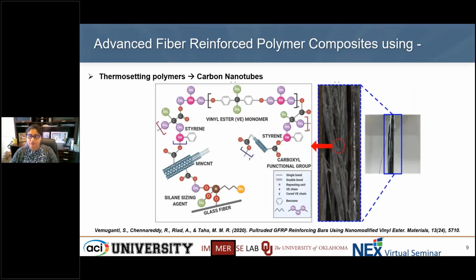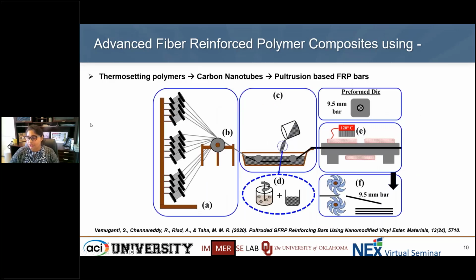One of the primary things we've seen with bars, for example, is that the silane sizing agent on the glass fiber or carbon fiber bar itself bonds really well with the functional group on the carbon nanotube. So the surface-treated carbon nanotubes really bond well with the silane sizing agents of FRP composites. That's why we're seeing all the different kinds of improvements that we are. For this particular project, the paper right here can give more information. This is work done at the University of Oklahoma, with me as a PhD student.